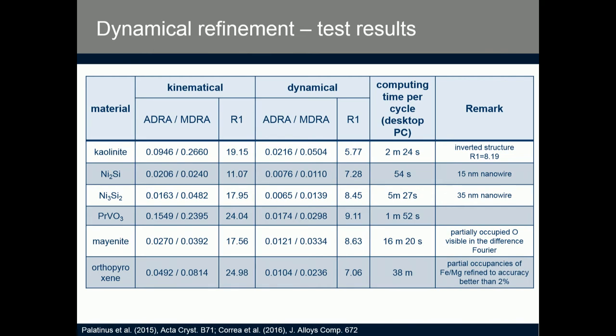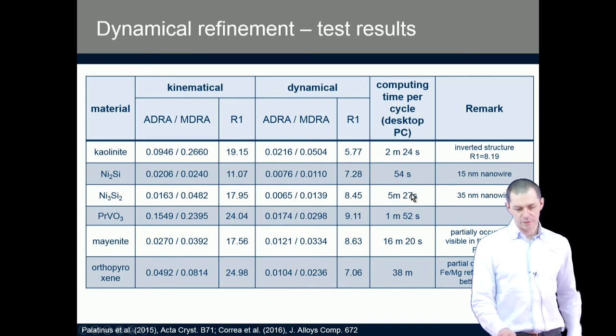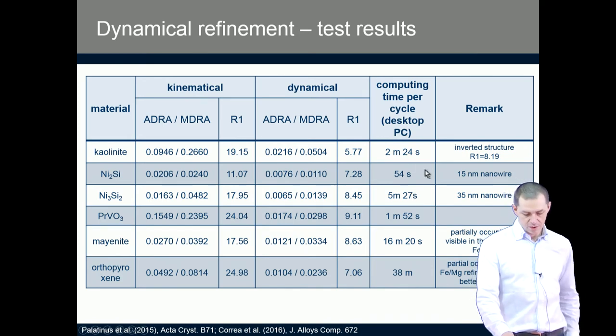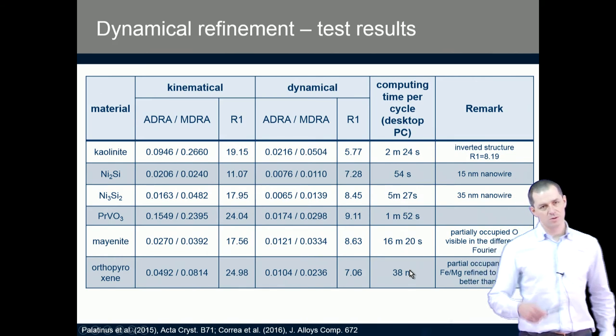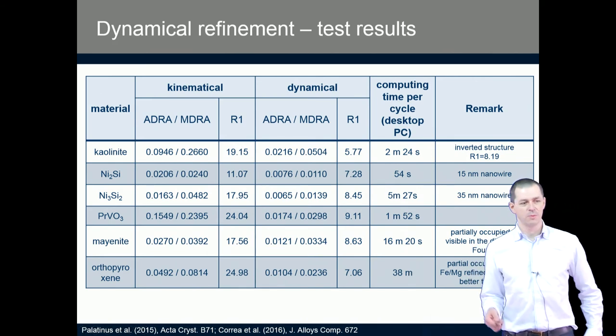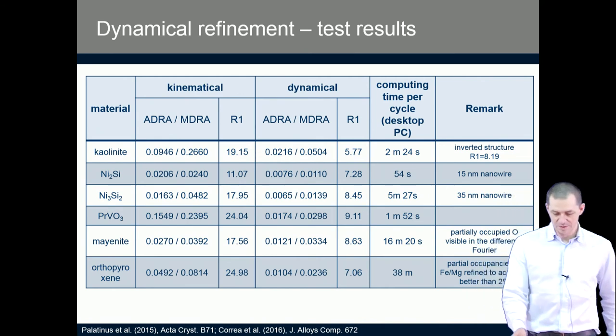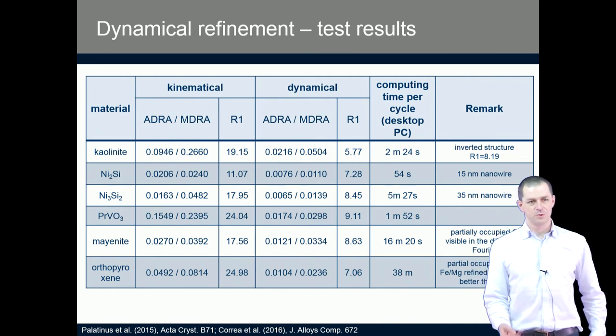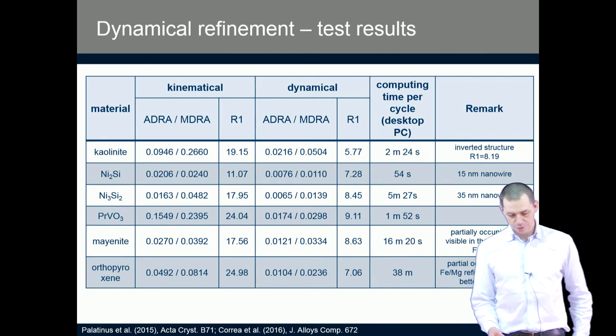do the dynamical refinement. This is the computing time per cycle on the normal desktop PC. So you see mostly it is in minutes. For the most complex structure of orthopyroxene, this was 38 minutes per cycle. So then you can drink a few cups of coffee before the refinement is done, but still it's a matter of maybe one day to get the refined converged structure.